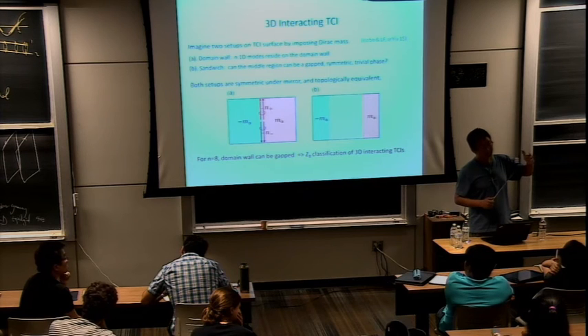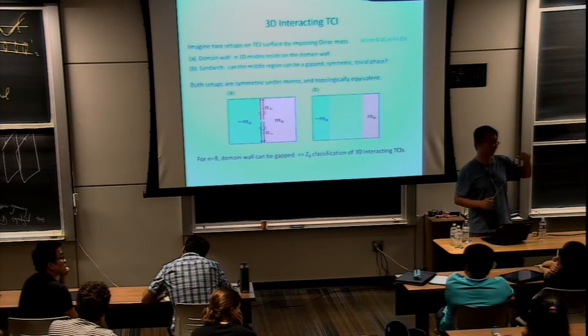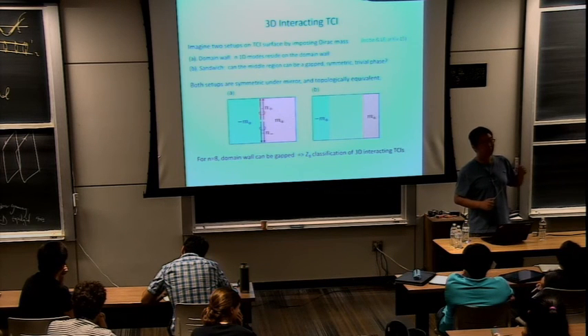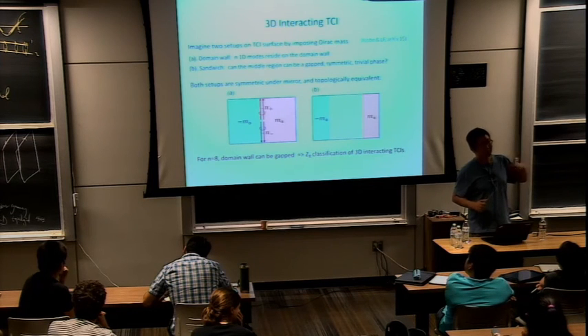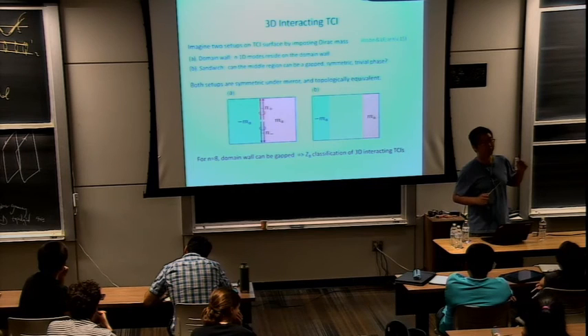Now, if I have weak disorder in the bulk, the topological phase cannot immediately go away, because topological states are robust due to the presence of the energy gap. So even if I have small disorder in the bulk, it's still robust. But if I have sufficiently strong disorder in the bulk, then the bulk can go through a topological phase transition to become a trivial Anderson insulator. But that's the same for all topological classes.